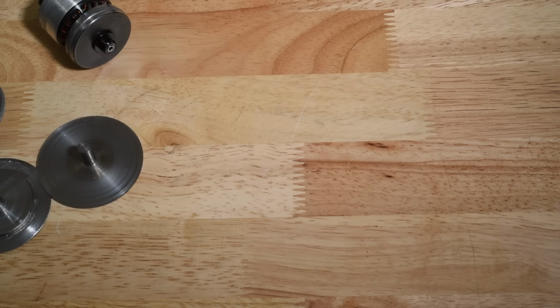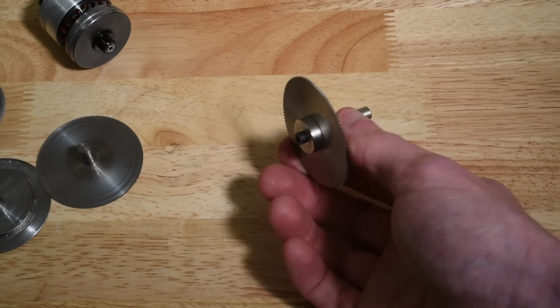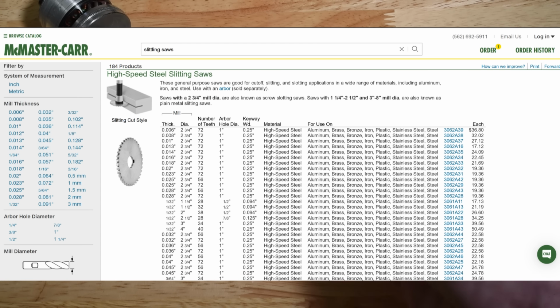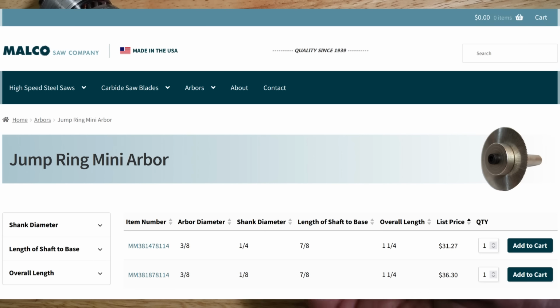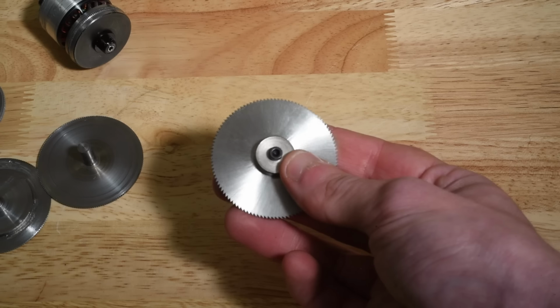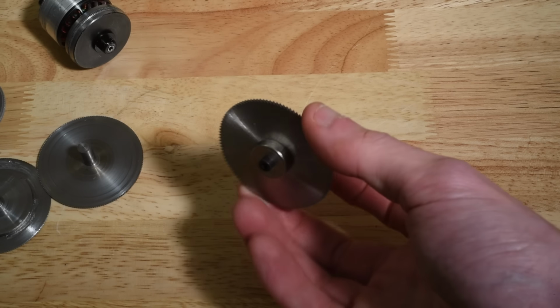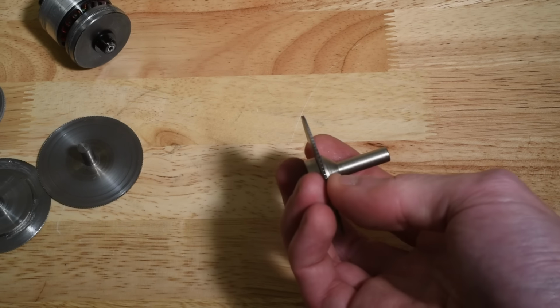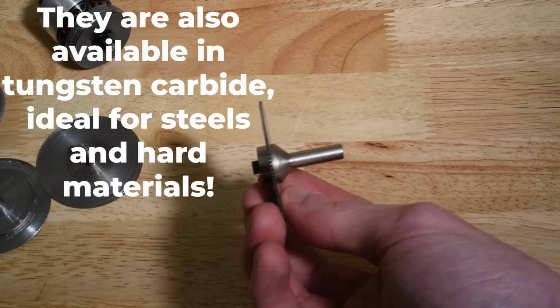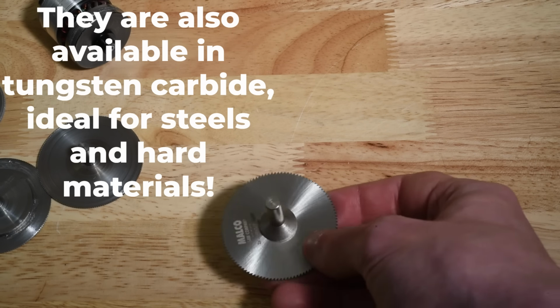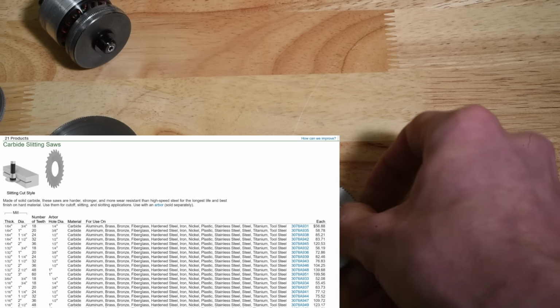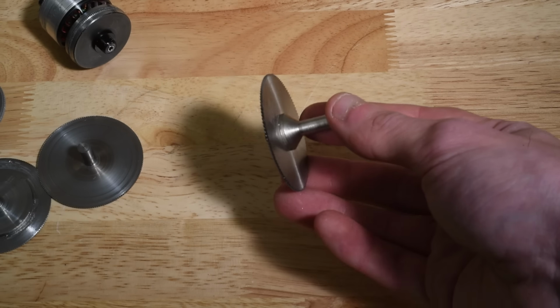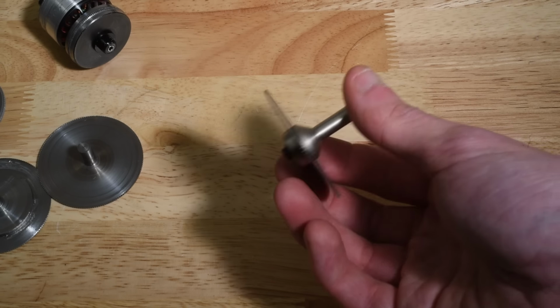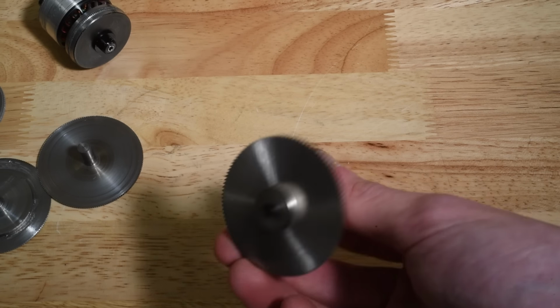So we went back to the drawing board again, and looking around at McMaster, we eventually encountered the concept of the slitting saw, which is a high-speed steel wheel which comes with a standard arbor of the right thickness that's nicely flared to provide support, and these saw blades are dynamically balanced to be able to spin as fast as 30,000 RPM. Plus, being made of already heat-treated and hardened high-speed steel, they have excellent wear resistance. They come in thicknesses from 3mm all the way down to 0.15mm, and they just do an excellent job of everything we were trying to do. We realized that we were trying to make our own saw blades from scratch, and we could just buy them for $6 or $8 next day shipping from McMaster. So, yeah. Buy commercial off the shelf when you can.